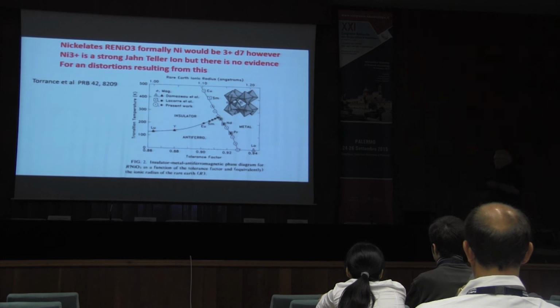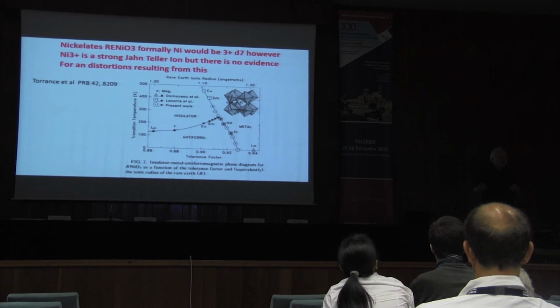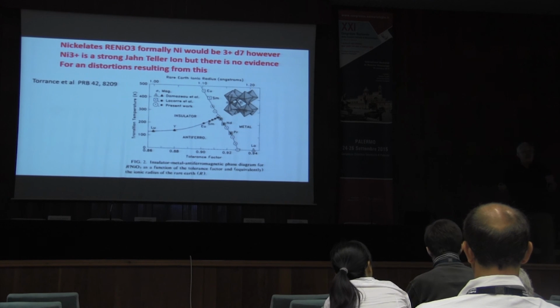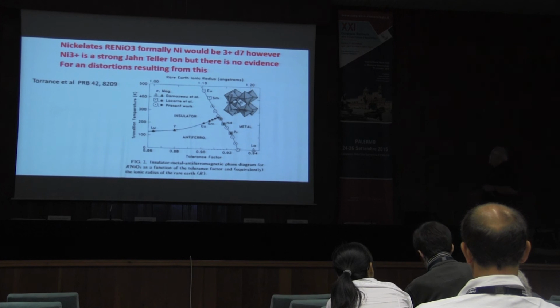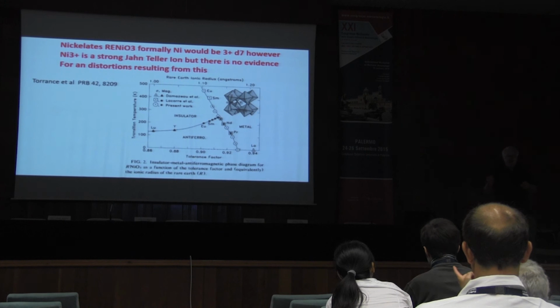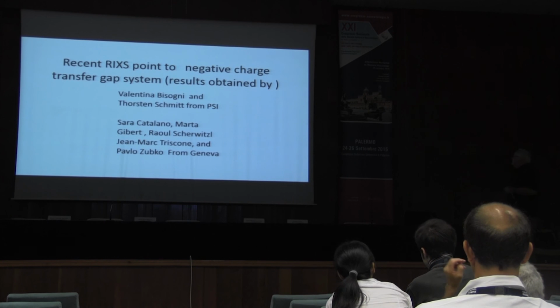Now, these are materials now that are being studied very much, because now with epitaxial growth we can finally get single crystals. We couldn't get single crystals of these materials, and therefore it never was quite sure as to what was going on. Now, with epitaxial growth, we can have single crystals, and with the new X-ray reflectometry and resonant inelastic X-ray scattering, we have the tools that can actually look at a thin film, epitaxial thin film, with a lot of signal. Okay. So there's a lot of things that actually came together.